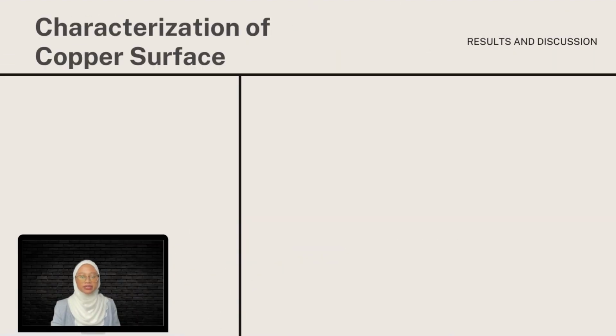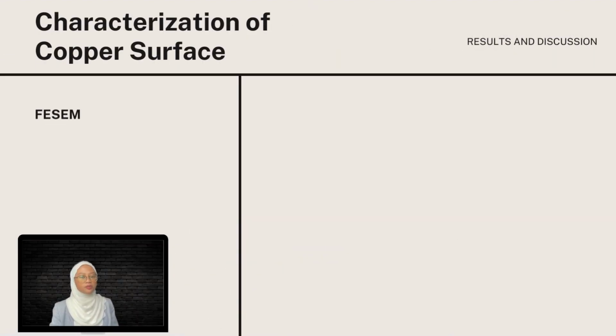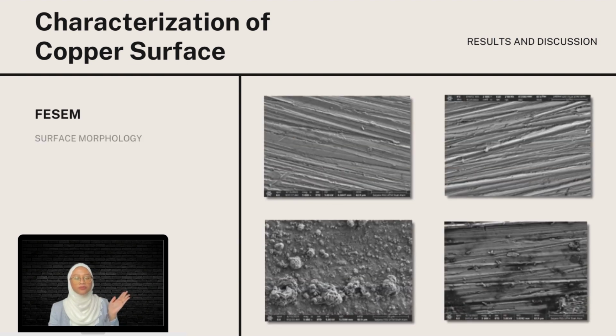Next is the characterization of copper surface under FESEM visualization. The 4 figures on the right show the surface morphology of 4 copper surfaces before and after immersion in the artificial sweat solution. The blank sample showed a smooth surface with polishing effect, indicating it was 100% copper, while the 0 hour sample showed no significant difference, which correlates with LPR data as there was not yet any reaction with the sweat solution. Hence, no deposition on the surface or no ions released.